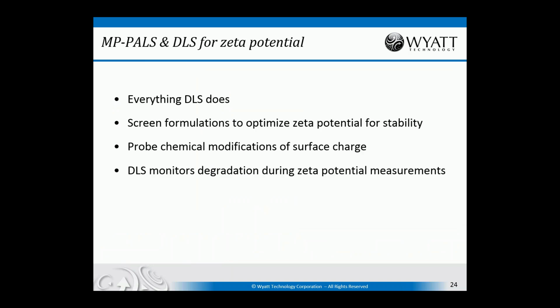So what are the applications of MP-PALS? Why would we want to use the combined MP-PALS DLS system? Well, first of all, it does everything DLS does because it has an incorporated DLS detector. In addition, it allows you to screen formulations to optimize the zeta potential and the stability of the formulation. If there are changes in the surface charge that are reflected in the zeta potential or net charge, they could be indications of chemical modifications to your system. So this could be a very quick and easy way of testing for chemical modifications on the surface of the nanoparticles.